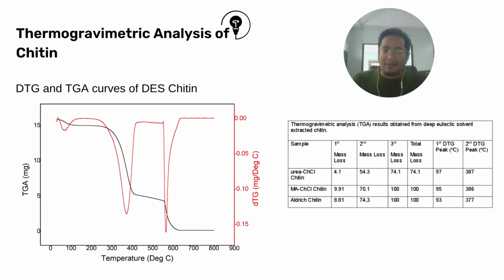For the thermogravimetric analysis of chitin, three decomposition steps were observed. The first mass loss, as seen in the figure, is correlated to moisture. The second mass loss is correlated to the saccharide backbones, which includes the dehydration of the saccharide rings. And lastly, the third mass loss is correlated to the carbonization of chitin.